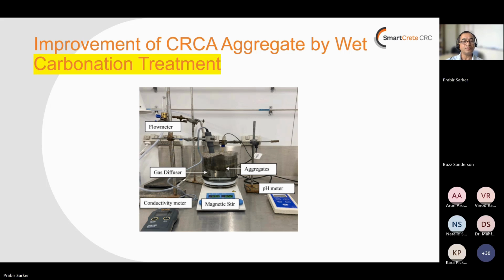So basically the carbon dioxide was flown through the water to diffuse it and dissolve it in the water, and then react with the calcium hydroxide that is available in the recycled aggregate to form calcium carbonate, to fill some of the pores and improve the ITZ or the adhered mortar with the aggregate. So that's how this method can contribute to improvement of the recycled aggregate.